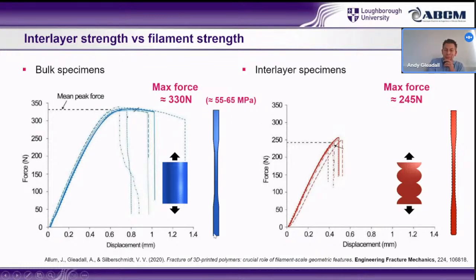So this is when we're printing in the X direction or Y direction and making the filament get narrower and wider by changing the extrusion rate. So when we're testing this, it's really continuous polymer that we're testing. This should be like bulk strength polymer, and it is from our tests. In the one on the right, it's now layer by layer by layer with lots of interfaces between the layers, lots of these grooves, and we're testing the force. And clearly, the one on the left sustains a higher force, and that's normally what we'd see and say the interlayer bond is causing an issue.